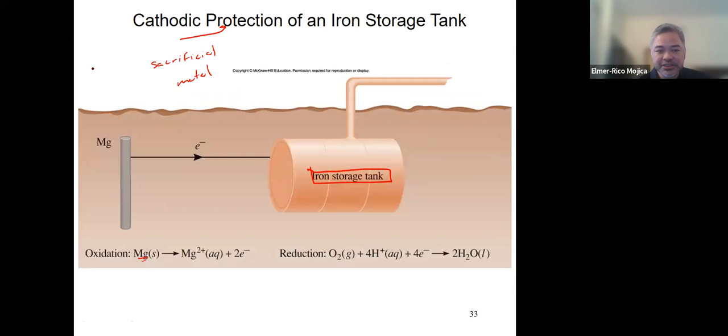Okay, because zinc has a lower reduction potential, and the good thing is it will form a zinc oxide that serves as a protective layer of your iron metal. And it prolongs by 2 times the lifetime of that roofing material. That's what happens in tropical countries. Okay, so that's a very good application of the knowledge of electrochemistry.